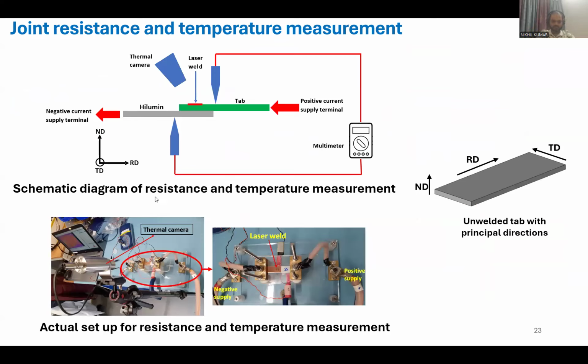And this is, as I mentioned, very important. Let's see this one: how I measure the resistance and temperature. As I mentioned, the resistance is a very important parameter. If you have an underweld, then this is going to dissipate your heat and you are not going to get that capacity, so your vehicle is going to discharge very early and very soon. So it's better to have a good weld so that there is very little heat dissipation from your joints, because the current will be transferring from the tab to the cell during charging and discharging as well. This is the main connection point from the cell to the tab, or cell to the vehicle engine. So, how have I captured the resistance?